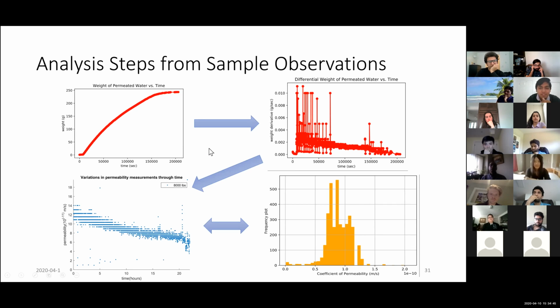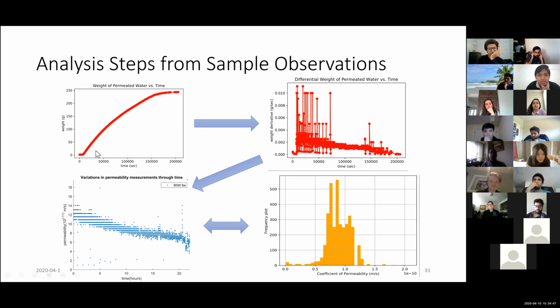So in terms of analysis of this permeability setup, what we observe is the weight of water that is permeated through the sample versus time. So we roughly get this kind of a curve from the sample. And then to get the permeability, I get the derivatives from this. So from this data, I get all the derivatives. And then from those derivatives of permeated water versus time, we can plot a permeability. This is a permeability distribution.